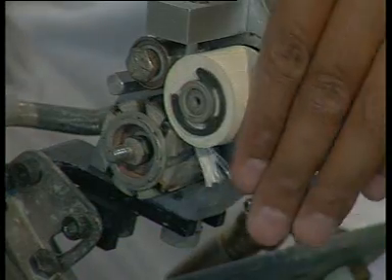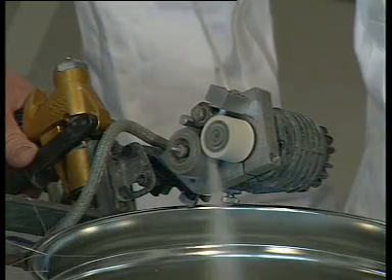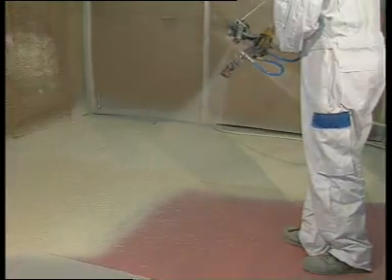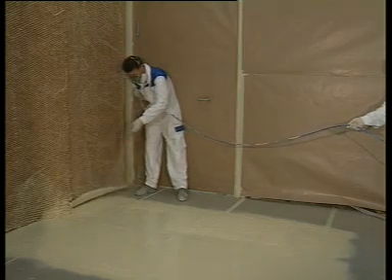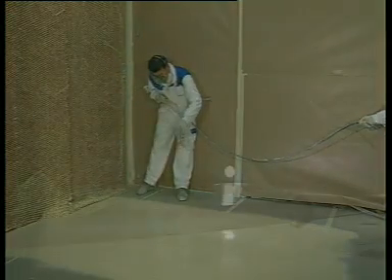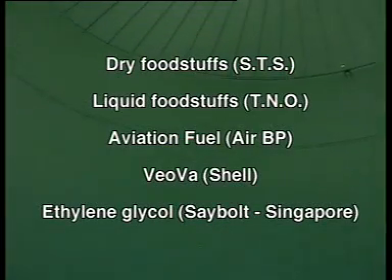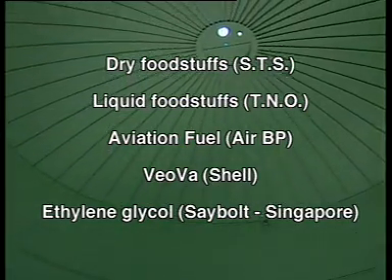Glass roving is fed into an air-powered cutter during the spraying process. Application is done using two airless spray nozzles. The glass and coating layer is compacted using a split washer roller. A single coat of unreinforced Novigard is then applied to complete the job. Various approvals are available, including certificates for the storage of jet fuel and dry food.